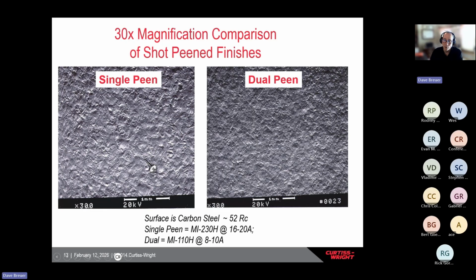For situations where you want to get more life without a lot more expense, you can shot peen it a second time, which we call a dual peen. In this case, it was shot peened a second time with a media that's about half the diameter - an 11 thousandths diameter at a lower energy. What you'll see is that the highest peaks from the first shot peen get pounded down, so you have more of a refined surface finish.